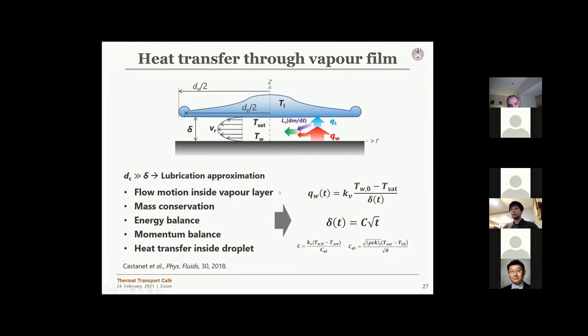From these submodels, we can eventually get the wall heat flux, which is basically heat conduction through the vapor film. What we have to know is the thickness of the vapor layer, since the vapor layer film grows as a function of time. So we can estimate the vapor layer like this.